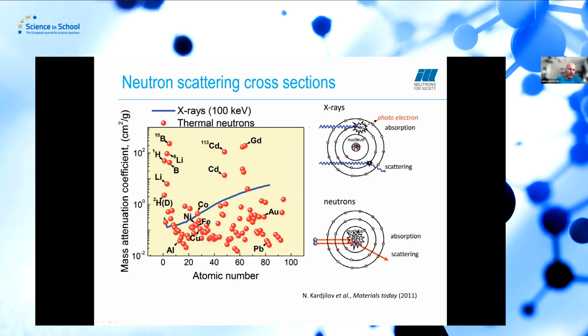And also, as already pointed out by Alessandro, you can very well distinguish hydrogen, for instance, from its isotope deuterium, which is just a proton with a neutron in the nucleus. And so you get isotope sensitivity. This you can, for instance, see also with lithium. Here you have natural lithium, sorry. And the 6 isotope of lithium has a much higher cross-section than the natural lithium.